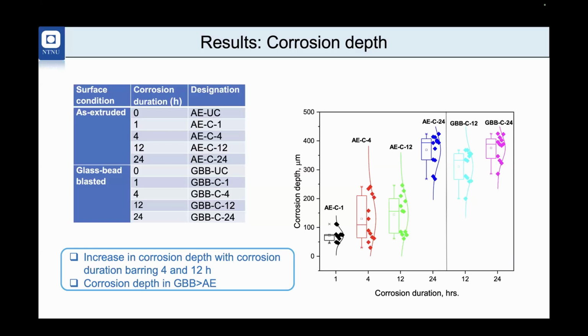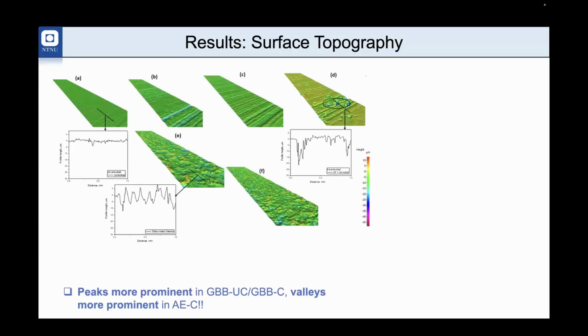And this is the same for the as-extruded as well as for the glass bead blasted condition. And we have also done some surface topography. As you can see, if you compare the as-extruded material, it is characterized by the extrusion lines, which are reflected as intermittent peaks and valleys.